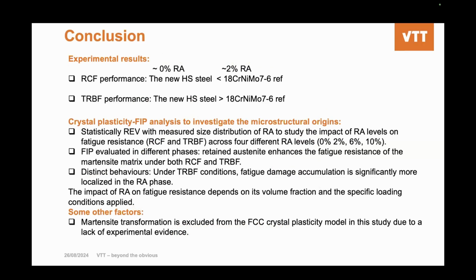Experimentally, we have analyzed two materials, one with 0% retained austenite level and another reference material with 2% retained austenite level. They showed different contact fatigue properties under rolling contact fatigue and tooth root bending fatigue. We have used crystal plasticity combined with FIP analysis to investigate the microstructural origins. According to the FIP evaluated in different phases, we found the retained austenite phase generally has an enhancing effect on the fatigue resistance of the martensite matrix. But we also observed a distinct evolution behavior under root bending fatigue conditions. The fatigue damage accumulation is significantly more localized in the RA phase.